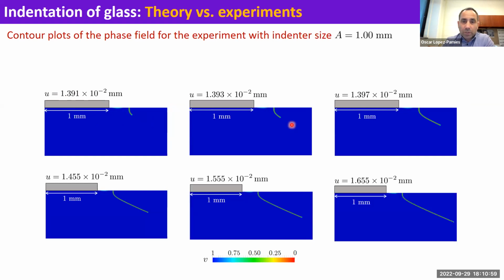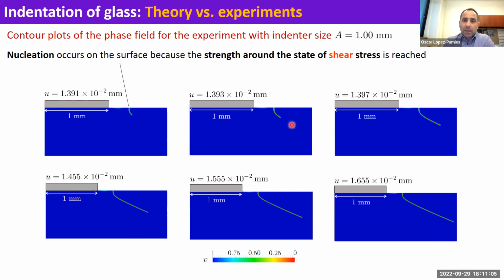So, okay, then we compare quantitatively. Qualitatively, this looks exactly like what happens in the experiment. You can see here that nucleation takes place on the surface of the glass, but not very close or directly below the indenter. The nucleation takes place away from the indenter at some distance.